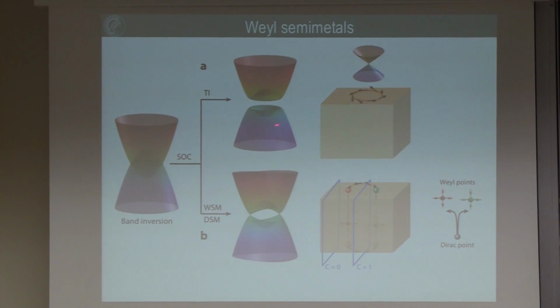In case of a topological insulator, we are hopefully insulating in the bulk, but this is also invented by physicists, so it's not really an insulator—most of them are more or less bad semiconductors. Anyway, they should be insulating in the bulk, and because of the band inversion and the topology change, they should have a special surface state, which is more or less protected, with a certain spin structure, and looks like a Dirac cone with linear dispersion, giving the interesting properties we already know from graphene.